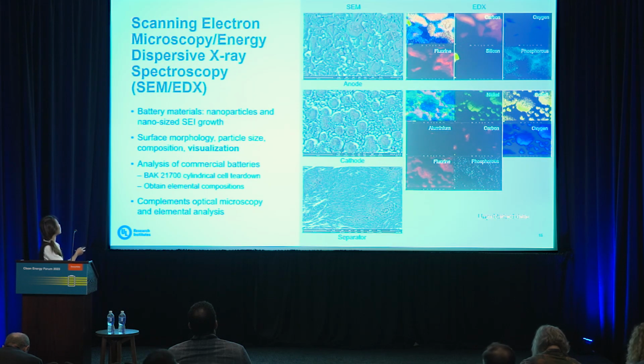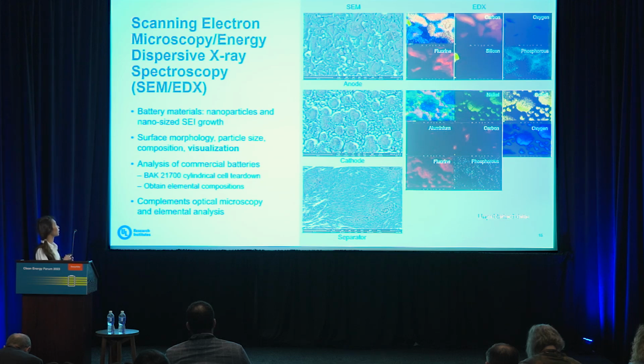So a very complementary method to this is SEM, scanning electron microscopy, which is coupled with energy dispersive X-ray spectroscopy, EDX. As I mentioned, the majority of battery materials are micron in size, but we still use some nanoparticles, for example, CNTs. Some of the processes that we are interested in, for example, the SEI growth, are also nano size, so we need another technique to look at these particles. SEM is a great way to look at it.